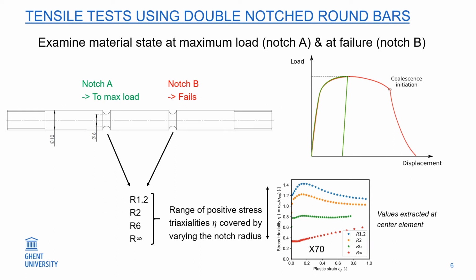Experimental data is required to calibrate the damage model. We performed tensile tests using double notch round bars, with the radius of both notches being equal. The result of using double notch specimens is that upon loading, both notches will deform almost equally. But when the maximum load is reached, the weakest notch of the two will start necking and go to fracture, while the other notch unloads elastically.